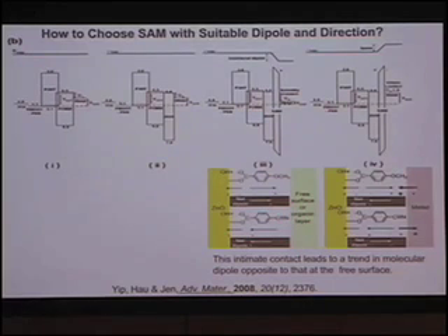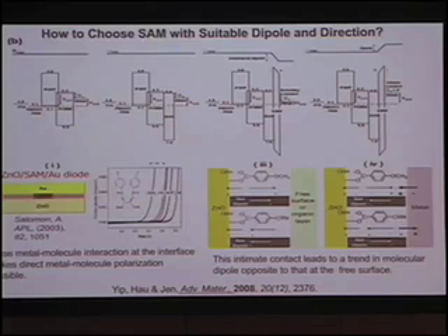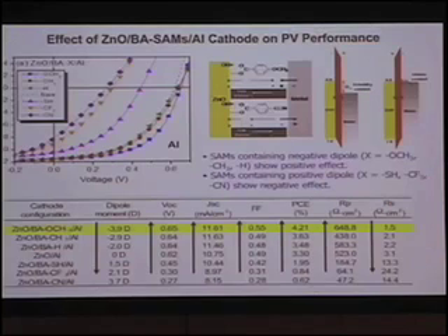However, when you start to slap a layer of metal, since you have a cathode, you slap it on top of this SAM, right? And as the metal and the molecule interface, when you slap a metal on top of that, you have a highly polarized interface. As a result, you generate another induced dipole here. This is a very, very large dipole, okay? So originally you have the dipole pointing in this direction, but with this large dipole, the net dipole actually points toward the zinc oxide direction right now, okay?